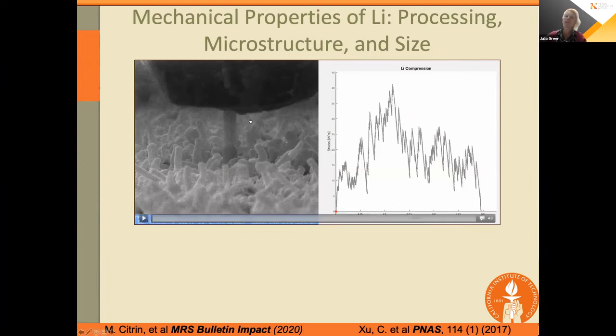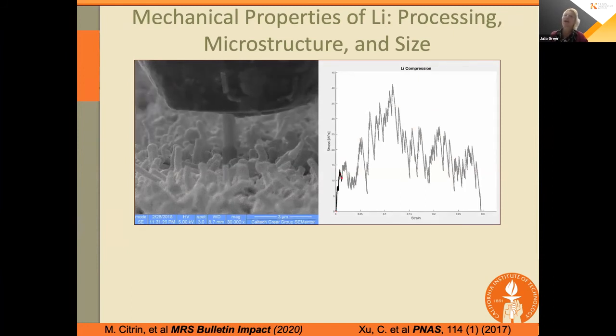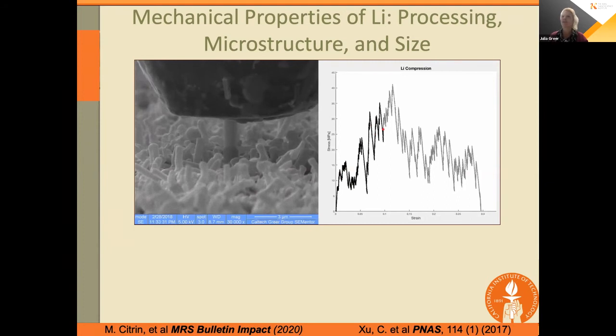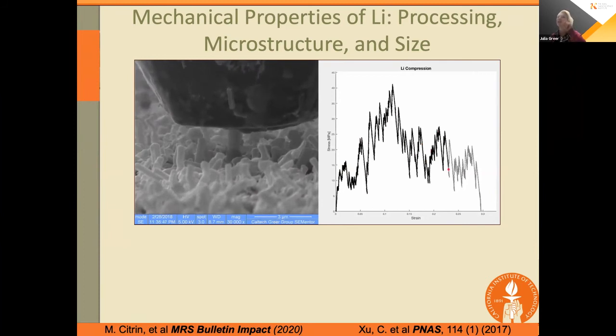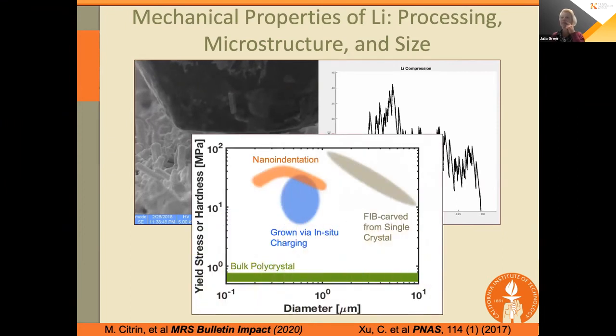So what you're observing here is a fully electrochemically formed dendrite, one of these individual dendrites that we were able to pick out in the sea of maybe 83 gazillion of them. And what we managed to do is to isolate a single one that's about 300 nanometers in diameter and to compress it mechanically to try to understand its strength under compression, because clearly they're very strong and there's something about the yield strength of lithium that maybe is being misunderstood.